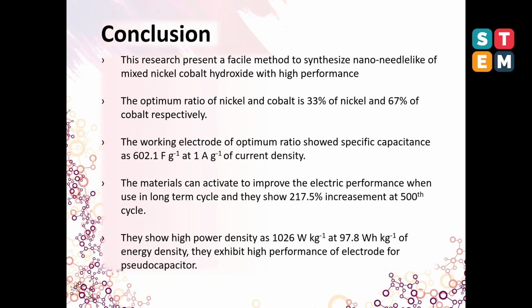For the conclusion, this research presents a facile method to synthesize nano-needle-like mixed nickel cobalt hydroxide with high performance, and the optimum ratio of nickel and cobalt is 33% nickel and 67% cobalt respectively.